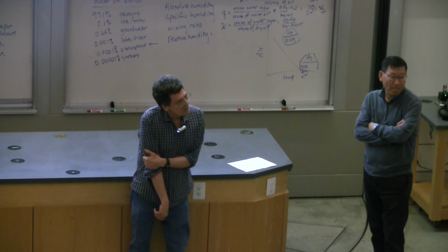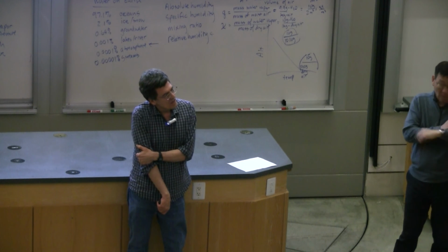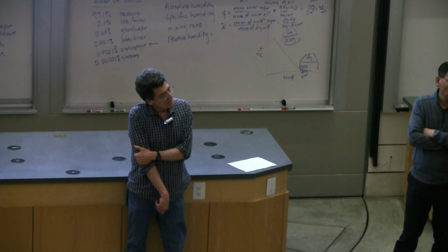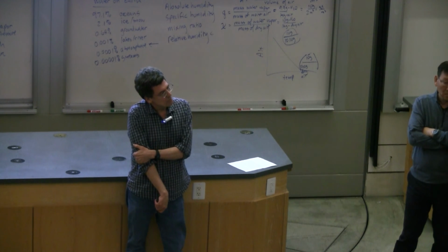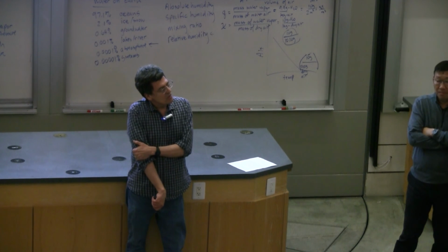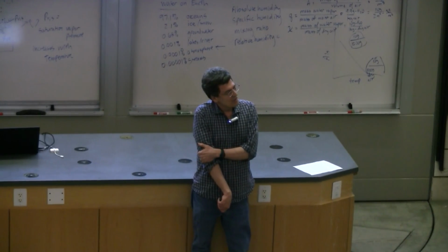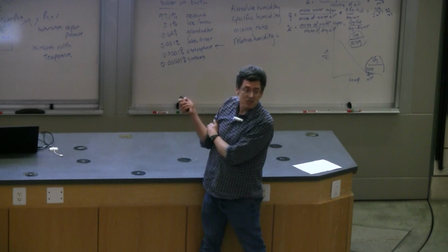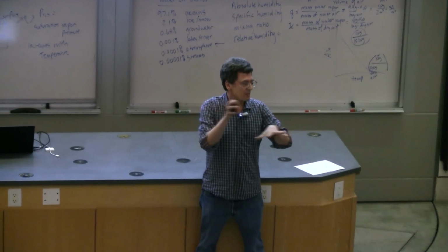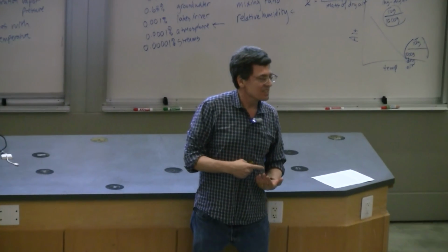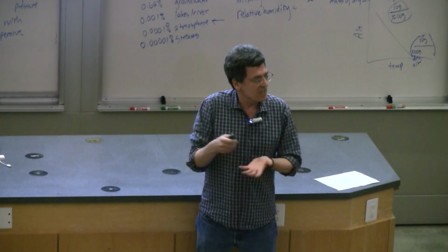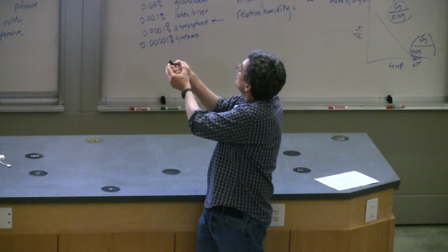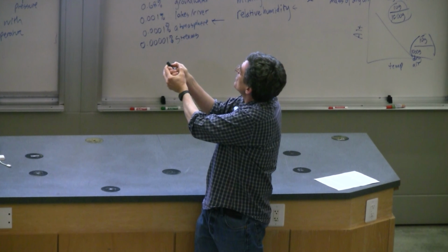And then last question. When you're changing the bias for the electron density, do you correspondingly change the tip bias, or do you, like the last stuff you showed on the model? Well, that should be independent, right? The patterns are independent of the tip bias. Well, the geometry of the patterns is independent, but the contrast is not. So what we do is we tune the tip bias to get contrast, but the actual patterns are determined by the top gate voltage and the bottom gate voltage.